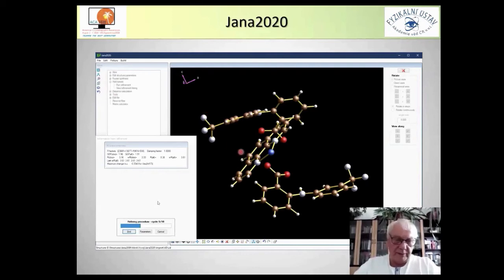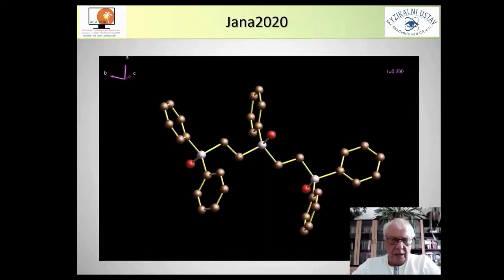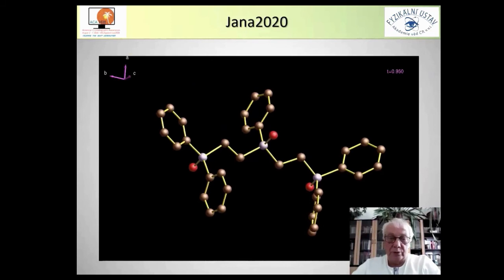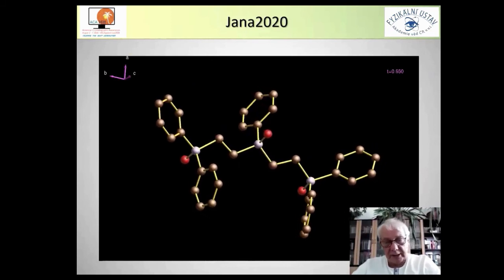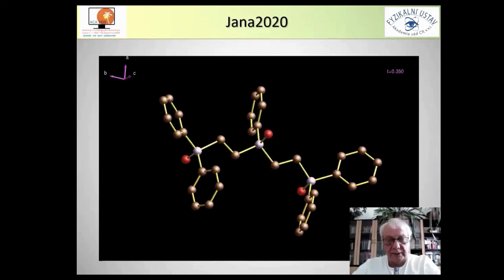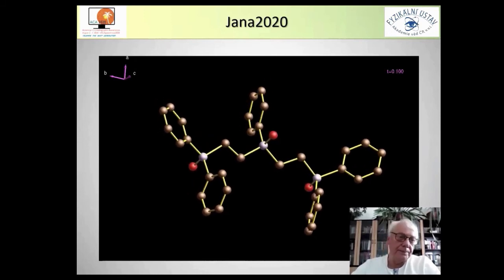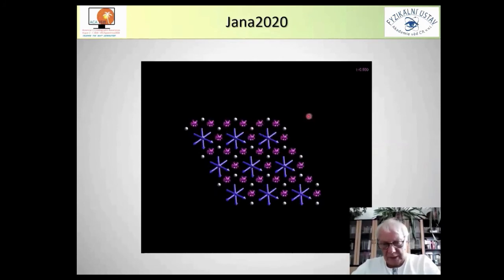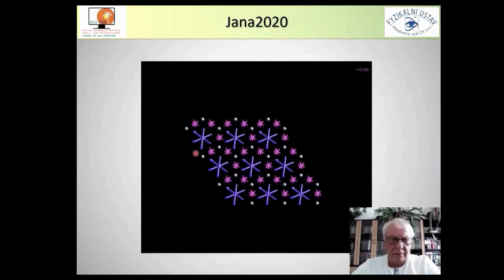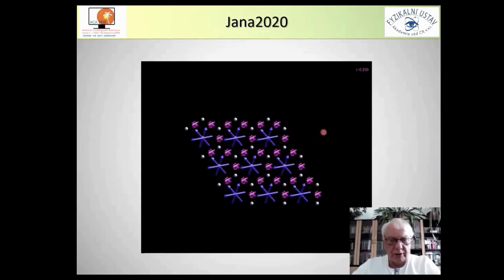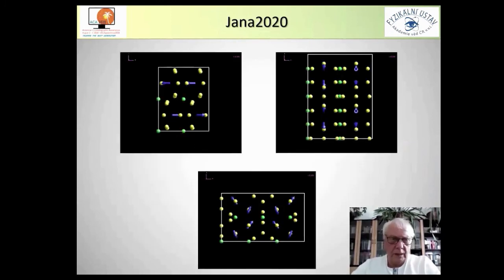For powders, you can do something very similar, and you can see how the profile is changing from cycle to cycle. Here you can see how the program can be used to show how the structure is changing by modulation. This one is for a regular structure, but the same algorithm can also be used for a magnetic structure, where we can see how magnetic moments change from cell to cell. Here you can see modulation in 3 different directions of one of my magnetic modulated structures.